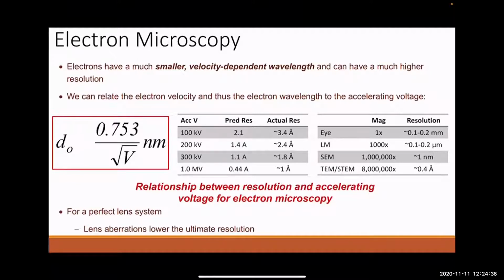And so you can see as you go to higher accelerating voltages, here's 100 kV, that's a typical TEM type accelerating voltage, 200 kV, 300 kV, up to even 1,000,000 volts. That used to be a thing in the 80s, 90s. They've sort of moved away from that with the advent of aberration corrected microscopes. But the idea is that you get better resolution, as you can actually see here.